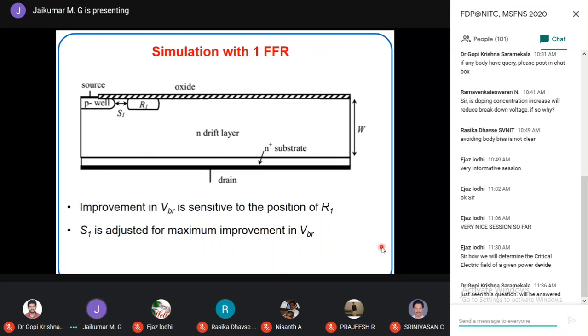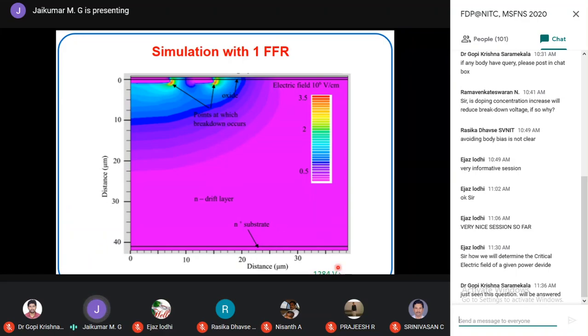Now a simulation with one floating field ring. How will the breakdown voltage be improved? This spacing, S1, has to be adjusted for maximum improvement in the breakdown voltage. After manufacturing that floating field ring, we have to adjust this spacing. So for the optimal spacing, the breakdown voltage was improved to 1284 volts. Now we can see that the breakdown happens at the edge of the half cell as well as at the first floating field ring. Both are simultaneously breaking down.